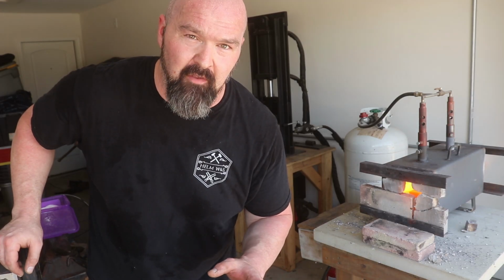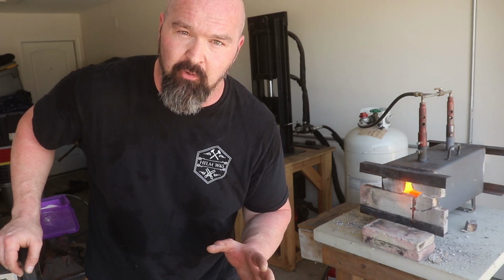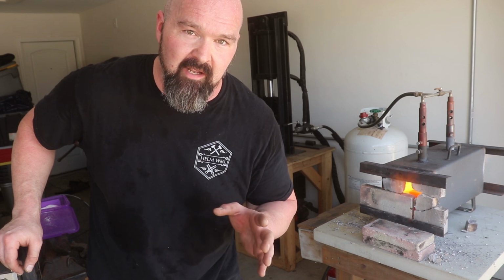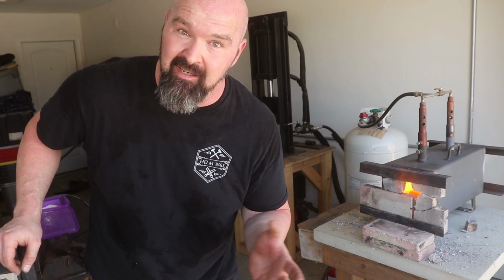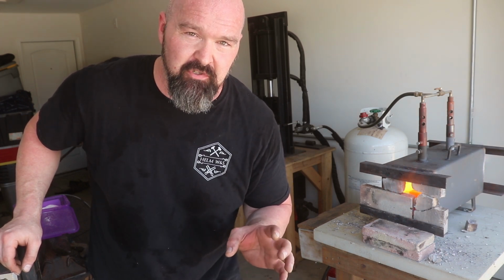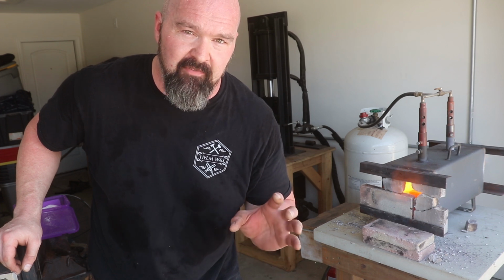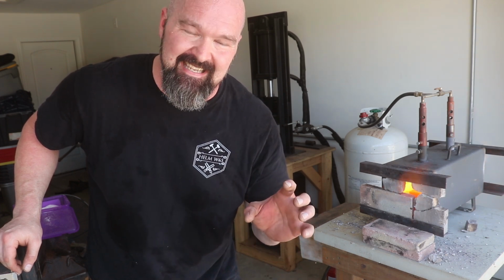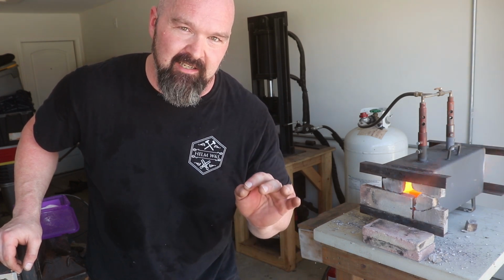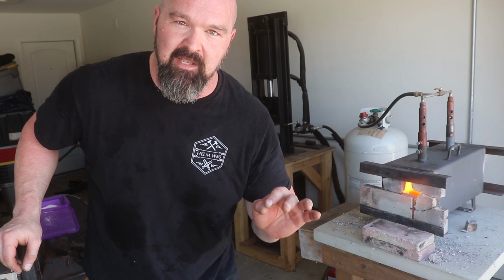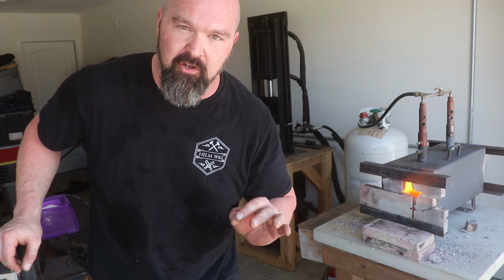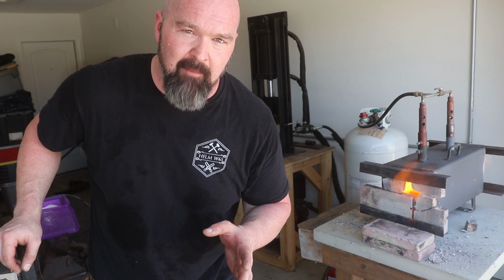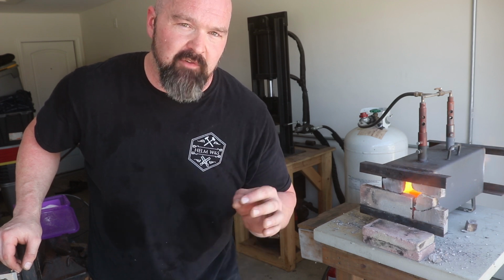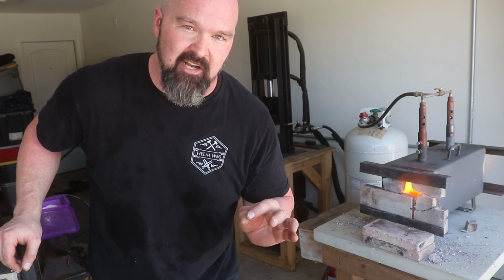I'm not going to take this out of the forge until it is basically as hot as my forge can possibly get it. You want to get it as hot as you can without melting it. You can really tell when you start to get close to the temperature because the top of the metal starts to look sticky. Basically it looks like just the very outside of the metal is beginning to melt. Then you know it's ready to go. But you got to also remember that that billet is very, very thick. So if just the outside is that temperature, that's not good enough.